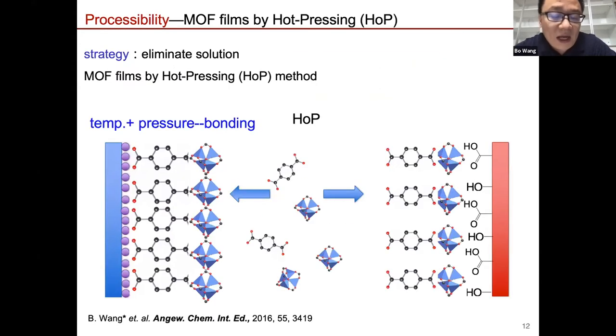So we introduced a very simple way of making films or coatings on different substrates. Here we call it the hot pressing method, or HOP method. It's truly a strategy where we eliminate solution. Instead of making it in solution, we make some MOFs without any solvents. We put in the starting material, the powder, and we cast the powder on the substrates, and then we hot press the surface. So you give energy directly to the material, and it's in a very restrained, confined space. The crystal cannot grow large. You will get a nanocrystalline thin film on the surface that way. So we call this the HOP method.